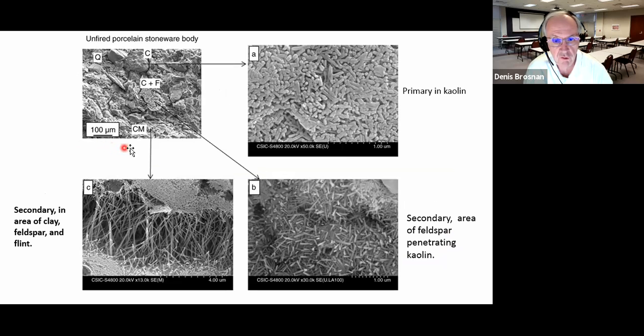Also, last time I showed you some photomicrographs of a body where primary mullite had formed on the kaolin crystals. Eventually, the feldspathic glass attacks those clay relics, and we get mullite needles developing more readily around the rim of the clay relics. And eventually, then we get a lot of crystals out into the pockets of glass, really providing what some people would say is a binder in this situation.